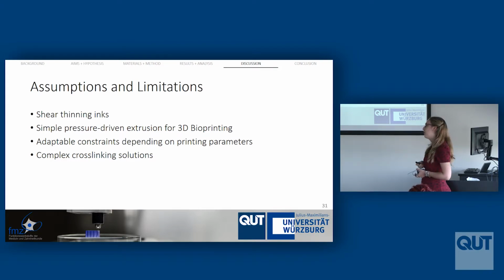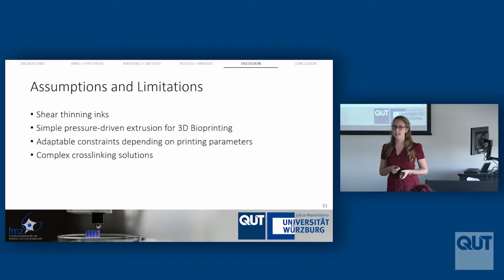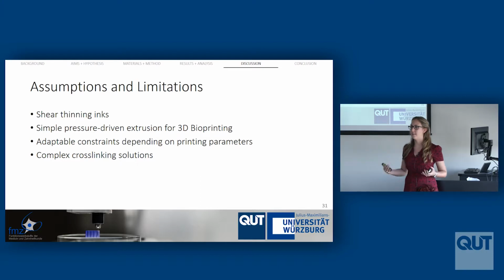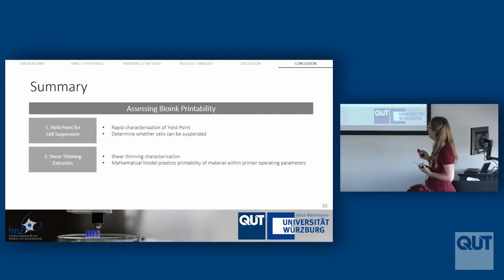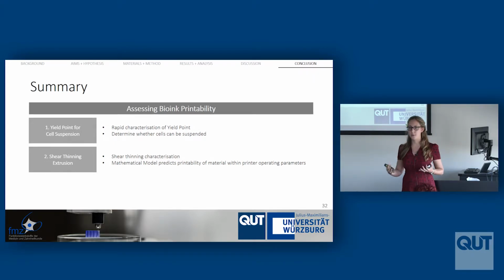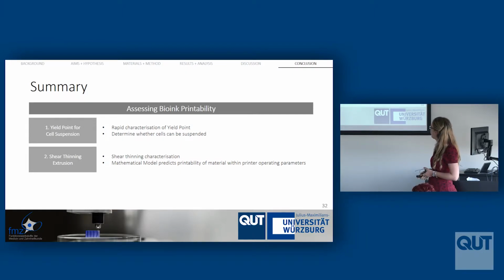There are also a couple of workarounds for this. There are other ways of cross-linking our materials to partially cross-link it, print it, and then fully cross-link it, or apply some different cross-linking methods as well. And so these all need to be taken into account when applying this mathematical model to new bioinks. But ultimately, we hope that with these two bioink printability assessment methods, we can characterize the yield point to tell if it can suspend cells or not, and we can check if it shear thin extrudes, which means that we're protecting our cells and able to make stable constructs that look exactly the way that we want to and have the right mechanical properties as well.